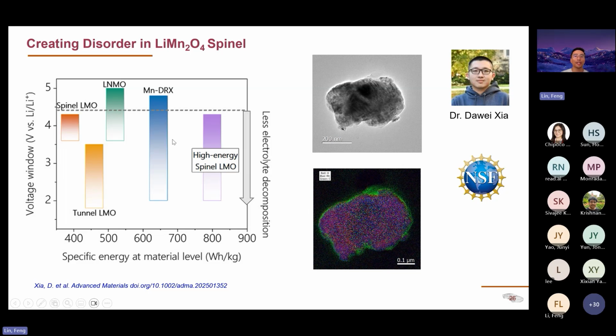And one thing that he did was he took the original commercially available lithium manganese oxide spinel, mixed it with carbon materials and performed ball milling. Once he performed the ball milling, he was able to get a carbon coating on the surface of the spinel materials. There is also some structural transformation. And in the end, he was able to get the materials level specific energy up to 800 watt-hour per kg, which is higher than a lot of the manganese-rich disordered rock salt cathodes my group is working on. And these are manganese-rich disordered rock salt charging up to only 4.5, 4.6 volt. We were not going to high voltage, otherwise you can go even higher energy density.